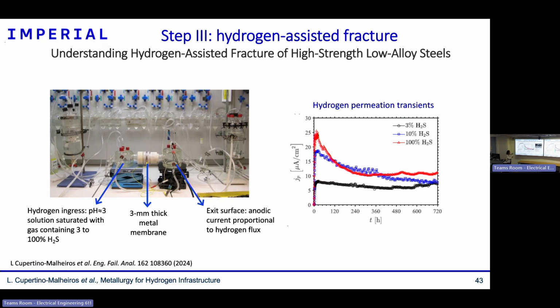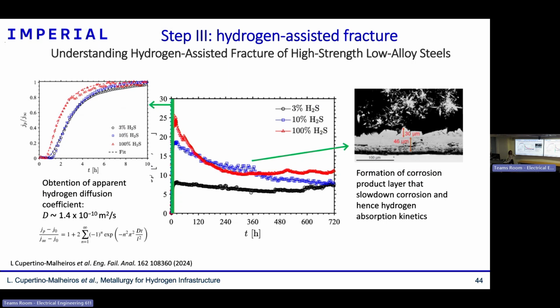Another thing you notice here is that over time, this hydrogen absorption tends to decrease. It decreases because hydrogen is entering the steel because of a corrosion process. And as the surface evolves, in those cases here with 10 and 100% H2S, there is a formation of a corrosion product layer that will slow down the corrosion kinetics and then slow down the hydrogen absorption. The benefit of doing these experiments is that when I'm doing my modeling, I can use this flux as a boundary condition and take into account those effects, the effect of the pressure of H2S and also the effect of the corrosion product on my simulations. Another thing that those permeation experiments give us is the diffusion coefficient of hydrogen in those materials, which is necessary also when we are doing diffusion modeling.